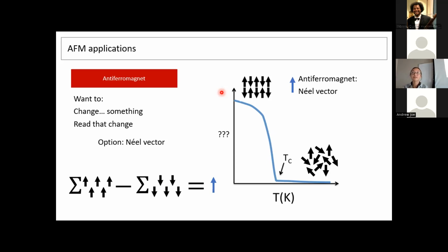Oh yeah, the question was, how do you choose which ones to add and which ones to subtract? So commonly, you'll think of an antiferromagnet as having sublattices. So this applies in this very special circumstance where we have everything pointing in one direction or the other. There are some more complicated orders where maybe a third of them are pointing in each of 3 directions, 120 degrees apart. But when you do have this nice order, which is called collinear, because they're all along the same line, then you're separating it out exactly by the ones that are pointing up minus the ones that are pointing down. Yeah. Thank you.